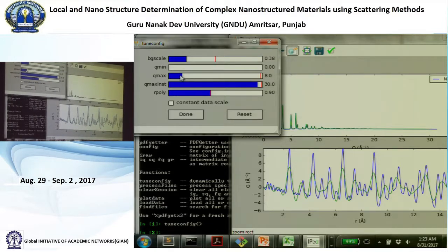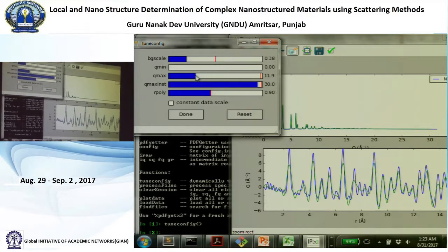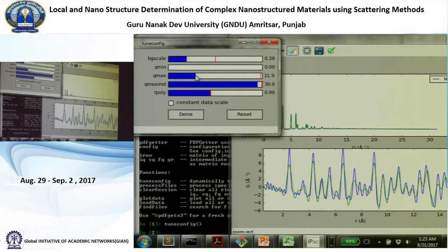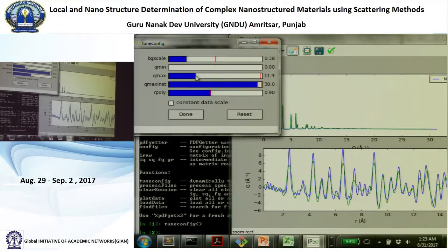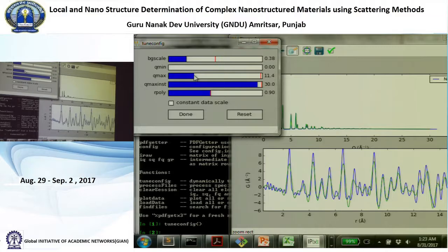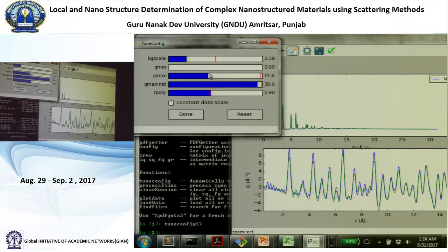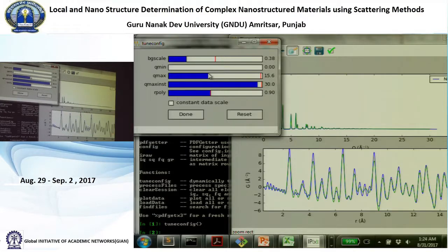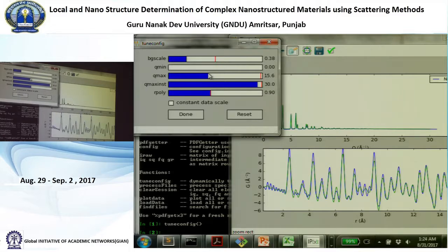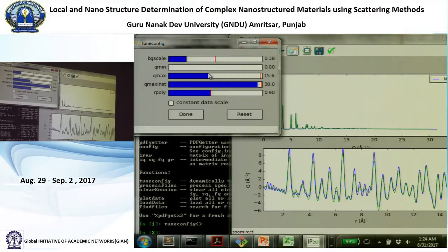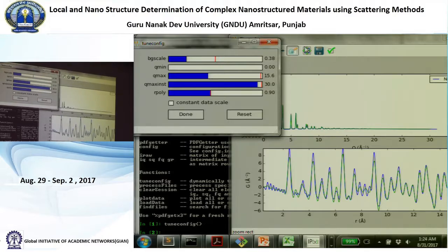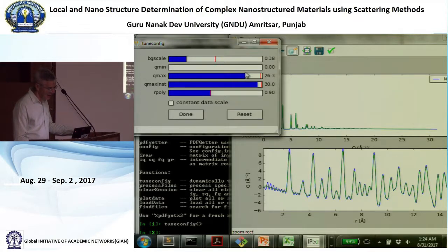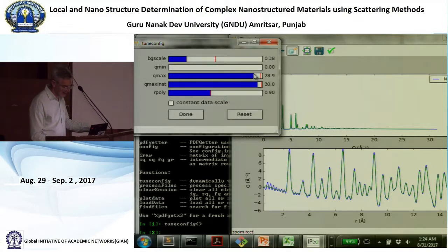If you have a moly tube and you measure to high angle, you can get to about 12. So the moly tube would give you a PDF that looks like this. It's starting to look actually very good. If you had a silver tube, you could measure to 15, and it's starting to look really quite good. Usually my recommendation if you're going to build a source in your lab is to build it with moly.